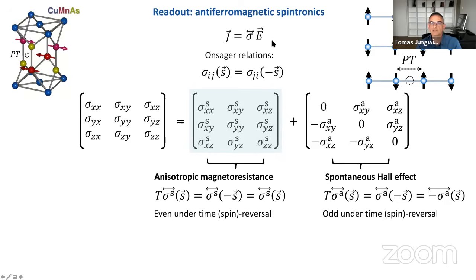And linear response conductivity is invariant under these operations of simple translation or inversion. So it doesn't matter if you do it or not. And from this perspective, such a simple model antiferromagnet behaves as if it had time reversal symmetry. So for the linear response coefficient in such a model, the anomalous Hall effect would vanish.